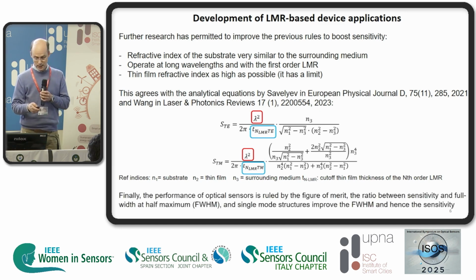But these equations only consider the sensitivity. If we focus also on the full width at half maximum, then we obtain the figure of merit. And the figure of merit gives more information than the sensitivity. The figure of merit is the ratio between sensitivity and full width half maximum, and it accounts for sensitivity and how narrow the resonance is, and this is related to accuracy. So we must boost both parameters, sensitivity as high as possible, full width half maximum as low as possible.